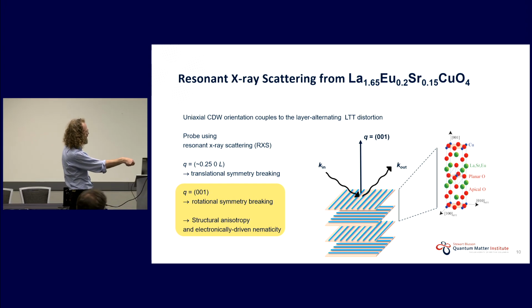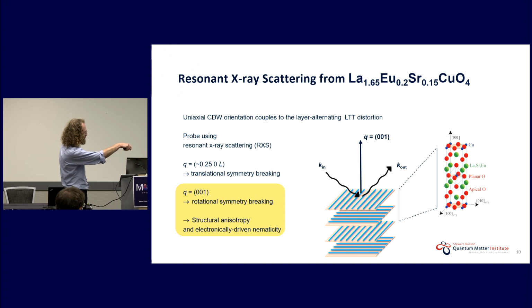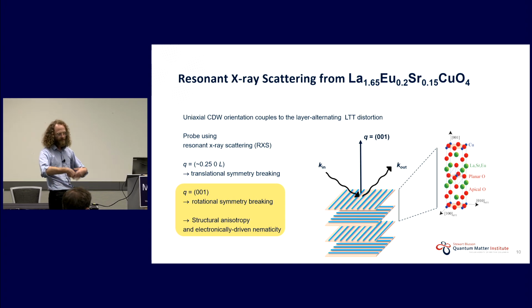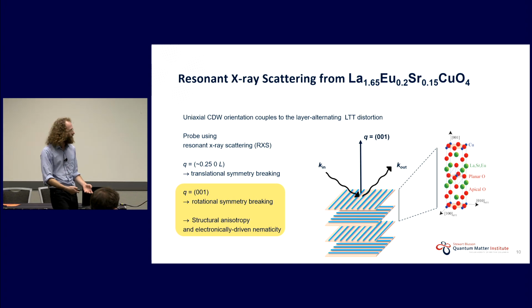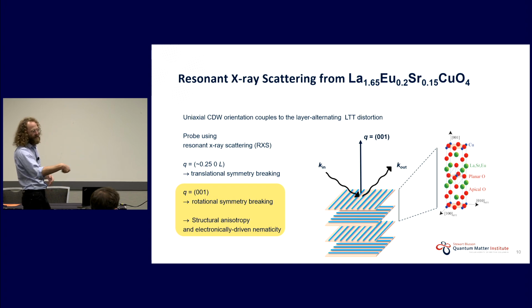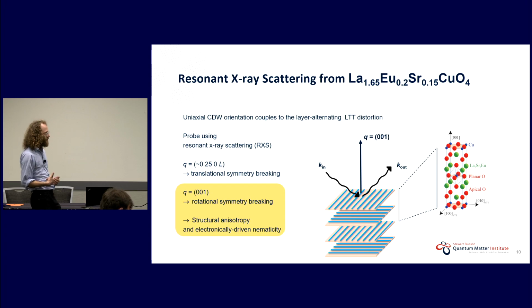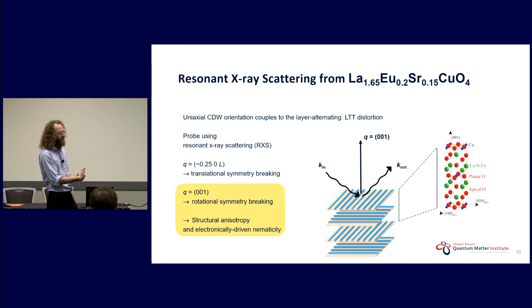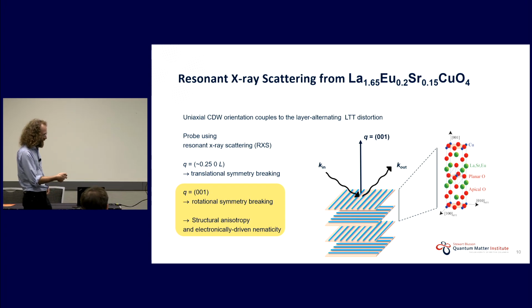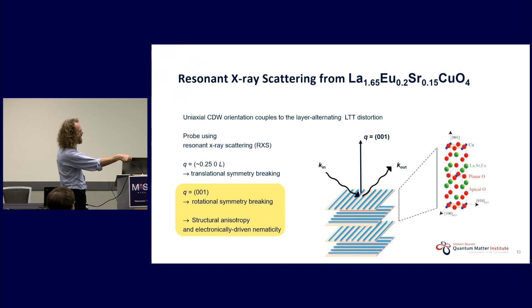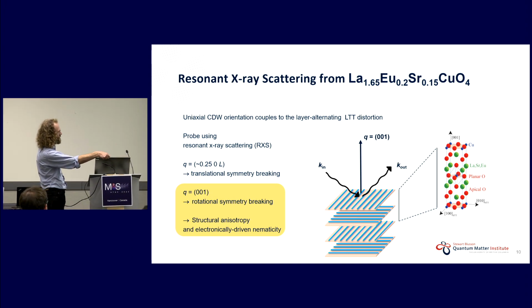this reflection is going to have now components which are both induced by the structural anisotropy, so purely associated with the anisotropy coming from the LTT distortion, but you'll also have additional anisotropy or additional rotational symmetry breaking or nematicity associated with the CDW itself, okay? So an electronic and a structural component. And we're going to try to pull those apart by using the spectroscopic contrast you get in resonant X-ray scattering.